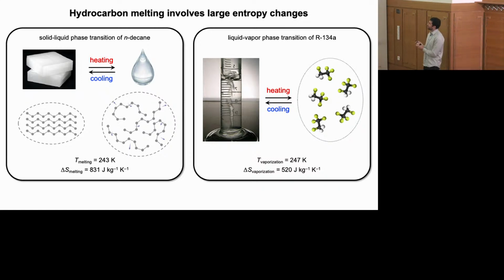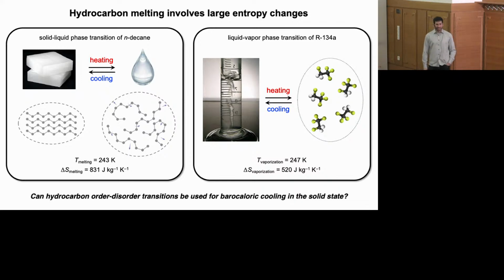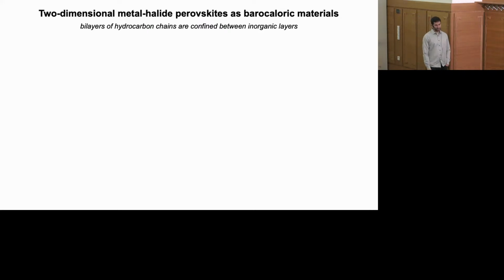And so we became really interested in thinking about whether we could have similar types of hydrocarbon chain disordering transitions in the solid state that might be useful for this kind of solid state cooling cycle. We were in search of different classes of materials where one has ordered arrangements of confined hydrocarbon molecules that can undergo thermally induced transitions to these disordered states, and we wanted to evaluate their potential for barocaloric cooling. The particular class of materials that we became most excited about are what's known as two-dimensional metal halide perovskites. I'll just walk you through a little bit about what these materials look like.